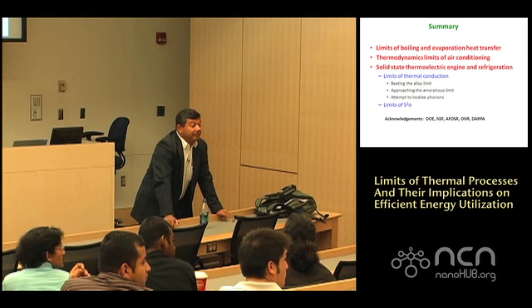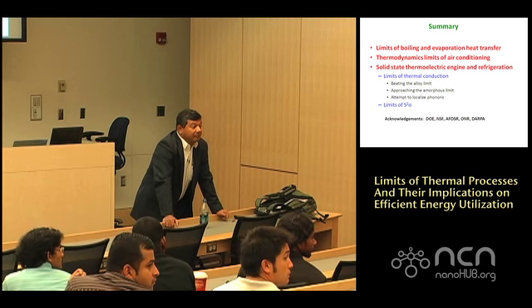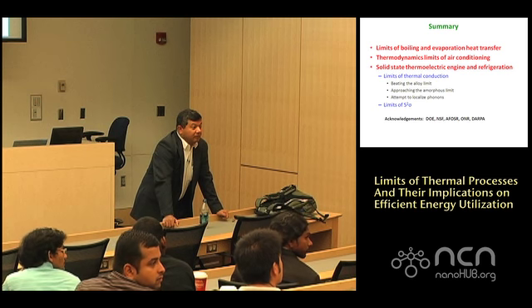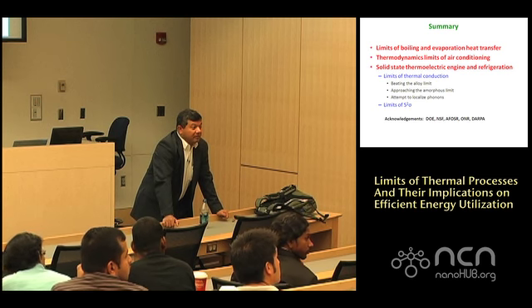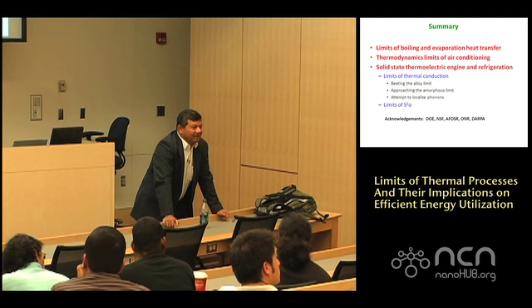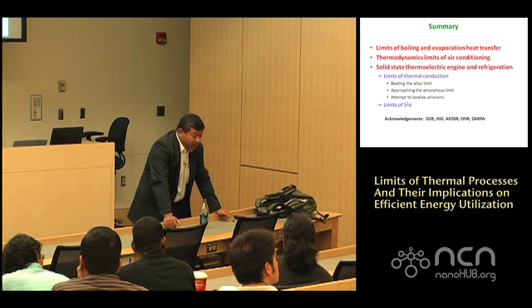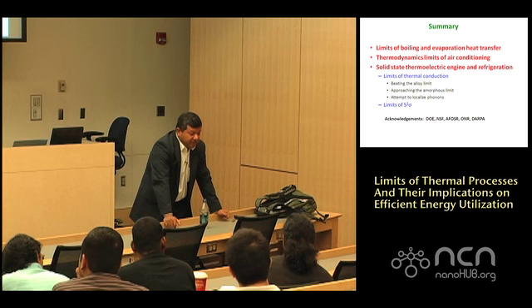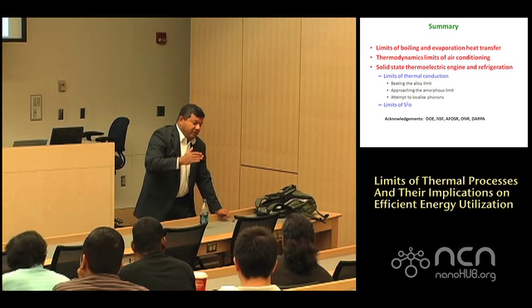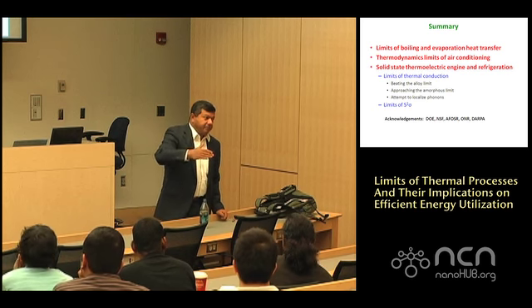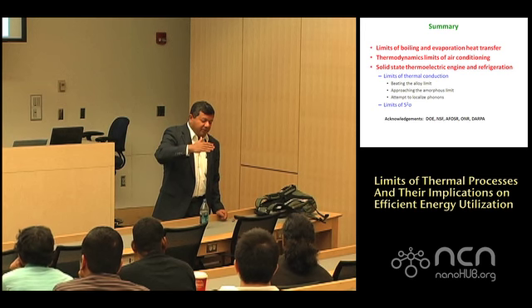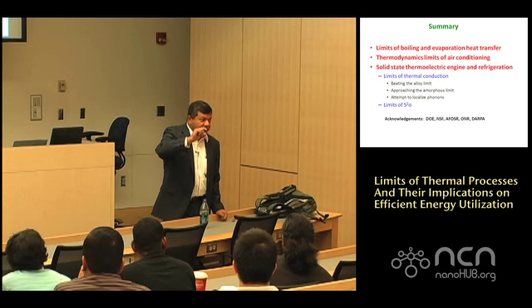When Art is growing those indium gallium aluminum arsenide alloys, are you adjusting the composition so that you get a small separation between the central valley and the satellite valley? You get a big asymmetry, right. Yeah, so I didn't talk about the electronic side of it. This is where John Bowers, Ali Shakuri, and Art Gossard come in. Art Gossard grows the materials, and it's actually digital alloying for indium gallium arsenide and indium gallium aluminum arsenide to control the band edge.